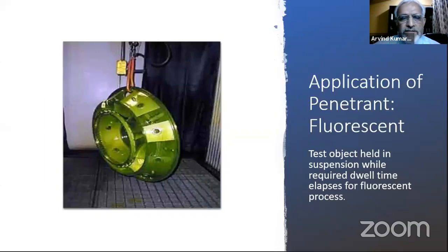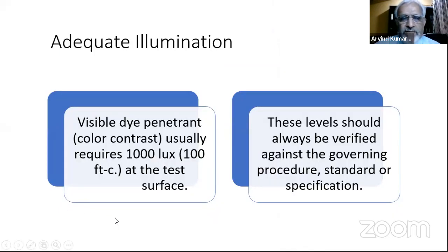These are just pictures only. The other requirement here is that for visible method, you need to have minimum lighting as specified in the code, which is 1000 lux. 1000 lux should be minimum lighting at the time of evaluation and interpretation of the indication. If you're doing a visible method, it is 1000 lux. If you're doing a fluorescent method, it is 1000 microwatt per centimeter square.